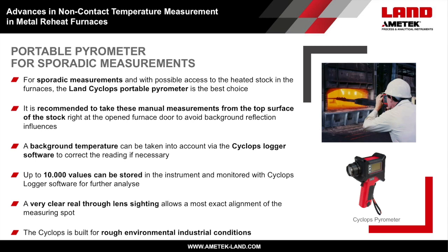These portable devices are used for sporadic measurements and with possible access to the heated stock in the furnace. It is recommended to take these manual measurements from the top surface of the stock right at the opened furnace door to avoid background reflections and influences. A possible background temperature can be taken into account via the Cyclops logger software to correct the reading if necessary too. Up to 10,000 values can be stored in the instrument and monitored with the Cyclops logger software for further analysis.